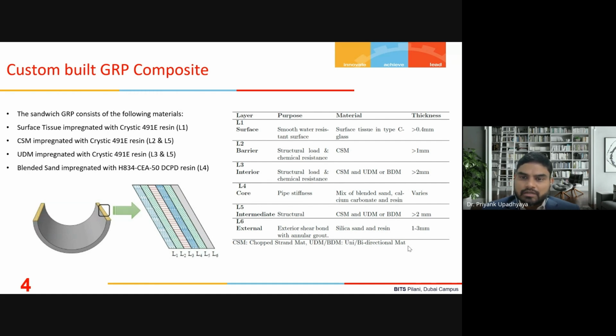The third layer is called the interior layer. That is again a mix of chopped strand mat or unidirectional or bidirectional mat. This is slightly thicker, around 2 mm. And then in between, to make the thickness bigger and increase the bending stiffness of these pipes, we add a layer which is made of blended sand and some resin. This is just to add thickness, so that the stronger layers, which are the glass fiber layers, sit away from the center line. The thickness of this varies based on the project that we are working on, but generally speaking, this is going to be more than 10 mm.